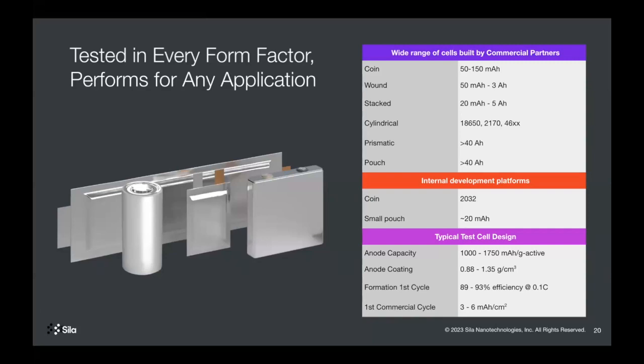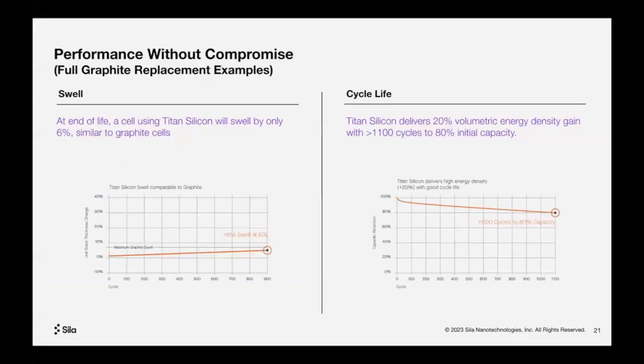Generally, you can see here the typical test cell design, and it depends on whether we're doing a blend or a full replacement of graphite. You can see the capacity of our material, the anode coating, the first cycle formation. So you can see the relevant data here. And as far as test results, the big thing with silicon material is swell. That's the one reason it hasn't been commercialized to date. It's always been the swell.